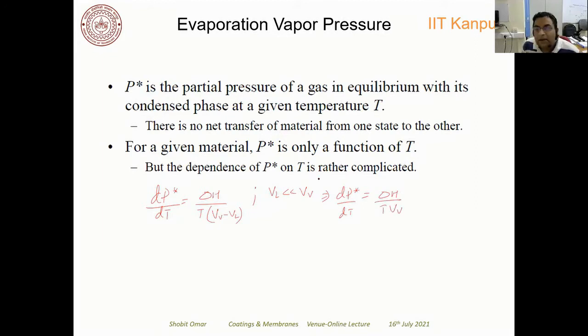Now, if we assume that these vapors follow the ideal gas law, then the volume of the vapor phase is given by RT by P star. If you input this here, what you will get is dP star by dT equal to delta H P star by RT squared.